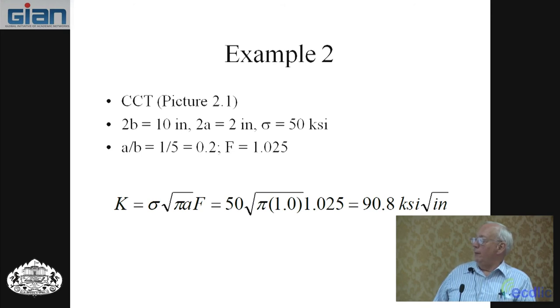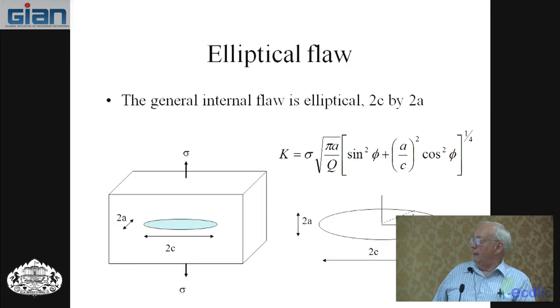Here's another example, the picture of the center crack. I use 2B because that's what Tada used. 2B is 10 inches, 2A is 2 inches, stress is 50. First thing is get A over B, 1 over 5 is 0.2, and then again 0.2.